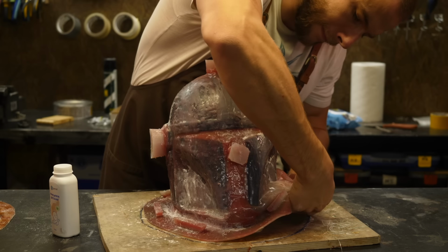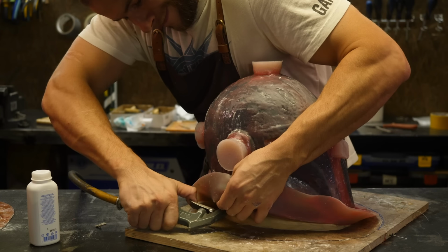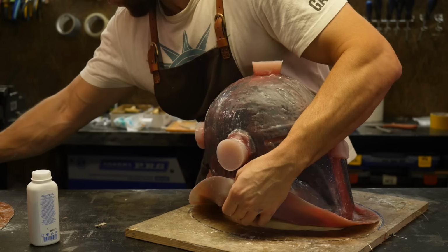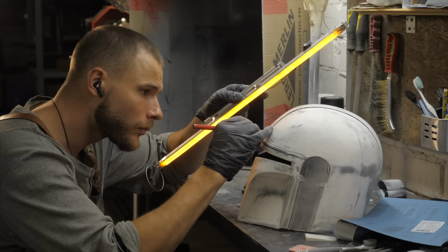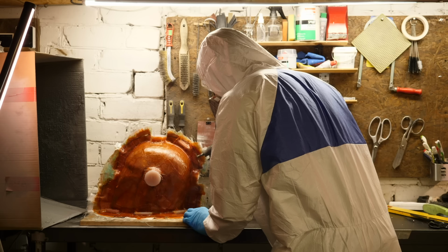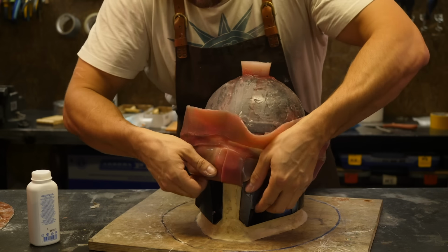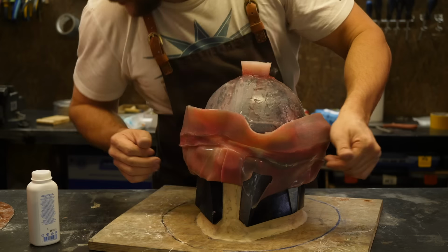Last time, for example, the silicone mold turned out to be too thin, but most critically, the extremely expensive release agent somehow didn't work at all, even though I did everything by the book. In the end, the silicone bonded permanently to the master model, and I couldn't even peel it off, at least to save the master model and not have to start from scratch. Only because of one faulty consumable, which, by the way, worked fine on the test samples but failed completely on the helmet, I ruined a month of work. This is why now I try to show in the frame the consumables that actually work.